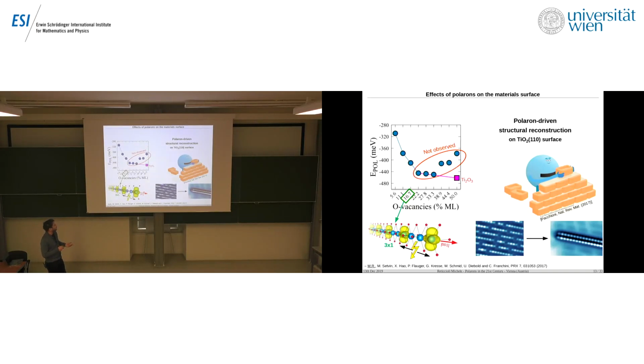and does not correspond to the observed concentration of oxygen vacancies in the experiment. So this was a very nice result, which showed how actually forming polaron on the reconstructed surface is more convenient than continuing to create oxygen vacancies and forming polaron.